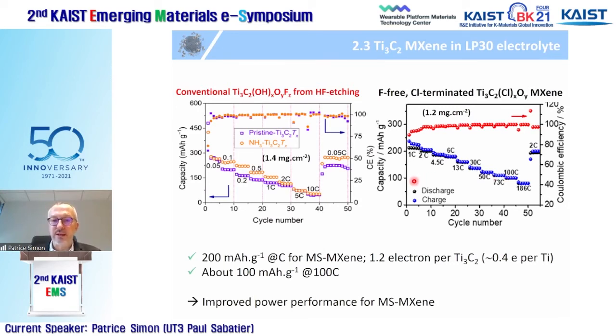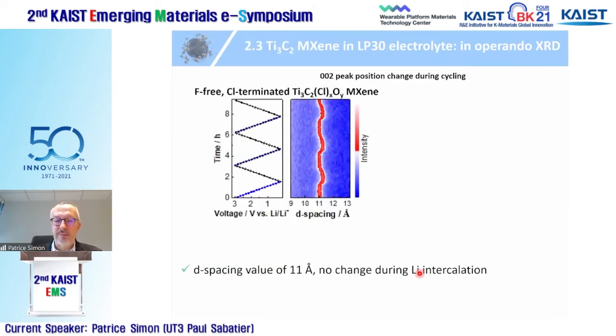So this is a 36 second discharge. This is a super high power performance for lithium intercalation in this material. So this MXene shows very high power performance and also high capacity. And what we did after was to track the position of the 002 peak during the cycling of this electrode.